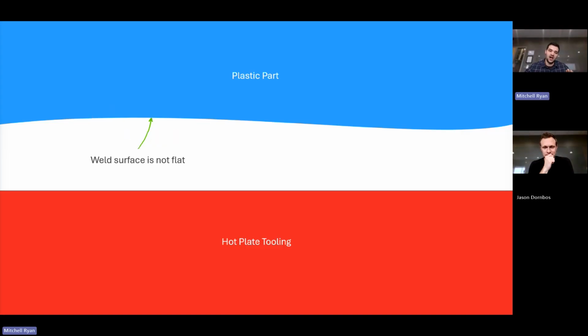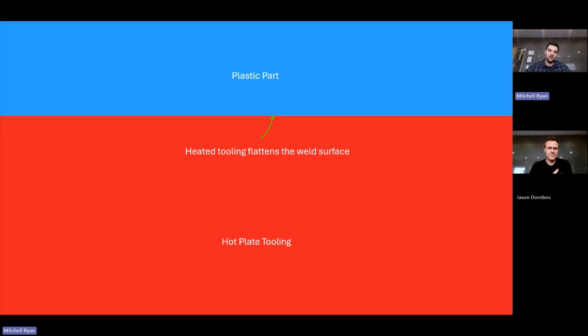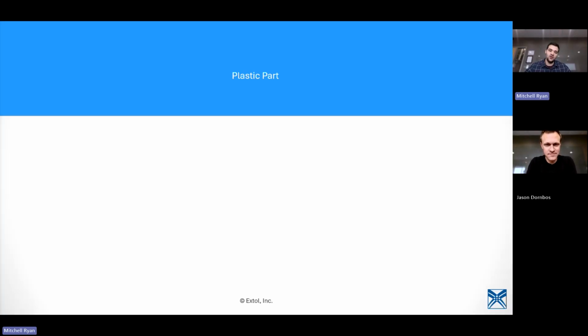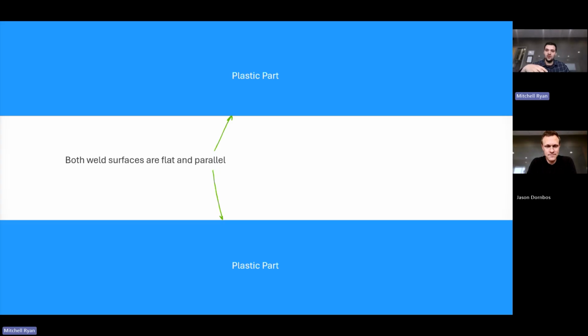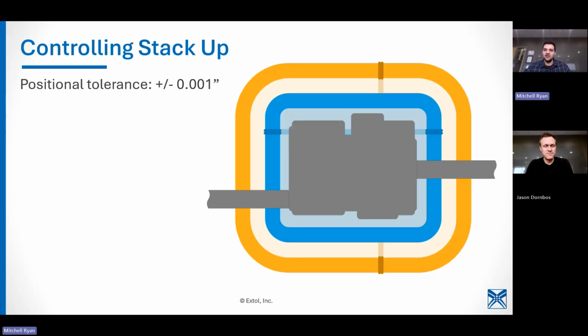So hot plate welding, you bring the hot tool in to contact with it, it flattens that weld surface. And then when you bring the two parts together, now you have two parallel surfaces, and both of those have an even force distribution across the surface. So that's why we like to use hot plate welding for those larger parts to take out the warp. So when we talked about surface area before, that's one way we address that question.